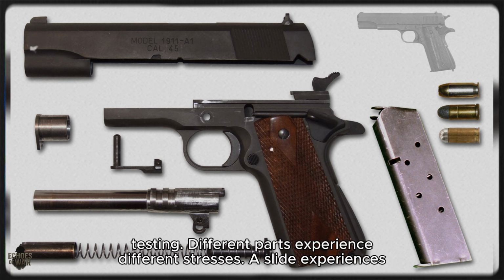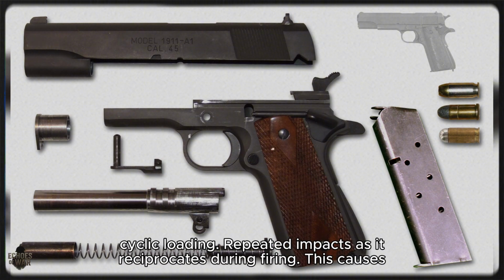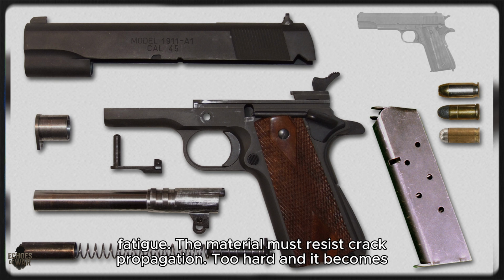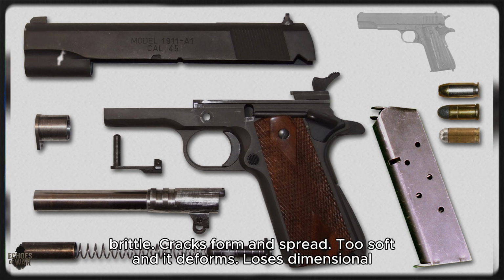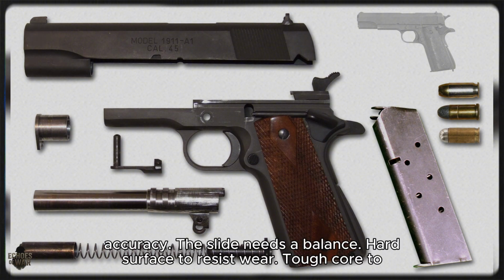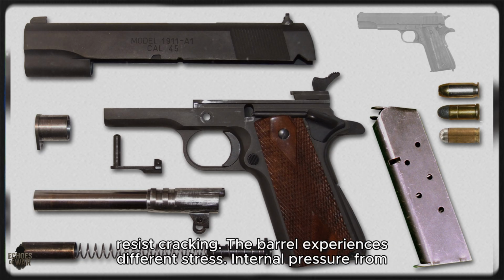Different parts experience different stresses. A slide experiences cyclic loading, repeated impacts as it reciprocates during firing. This causes fatigue. The material must resist crack propagation. Too hard and it becomes brittle. Cracks form and spread. Too soft and it deforms, loses dimensional accuracy. The slide needs a balance. Hard surface to resist wear. Tough core to resist cracking.